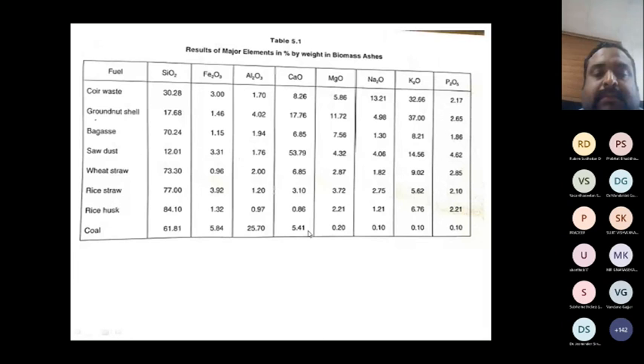Other things are very negligible. Whereas if you are going for co-firing with biomass, biomass has a lot of sodium and potassium. These are all fluxing agents. Here only the problem occurs. See, alumina and silica are very refractory materials, nothing will happen. Whereas when you are co-firing with biomass, these are all fluxing agents. These will bring down the melting temperature of the coal ash, since you are adding some fluxing agent in the form of biomass.